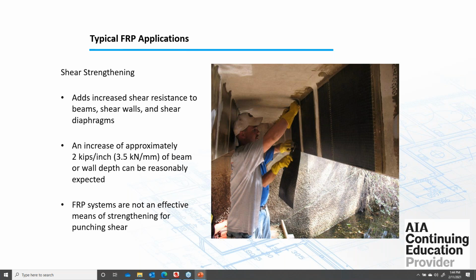And then lastly, FRP systems are not effective for punching shear. For anyone that's not familiar with that, if you have a column being supported on a slab, because of that concentrated load, it wants to punch through the slab. So they will put what we call a drop panel, or a thickened area of the slab, underneath where the column is. But if it's an older building and they didn't really understand the principles as much when it was built, there might not be a drop panel. So you might have punching shear where the column's punching through. Unfortunately, FRP is not effective as a solution to that.